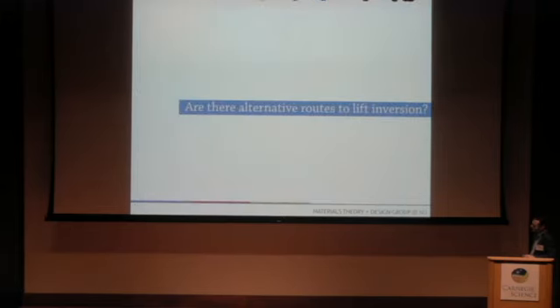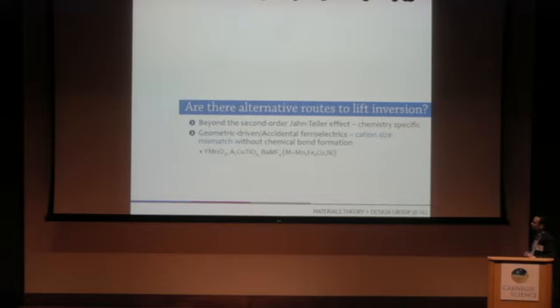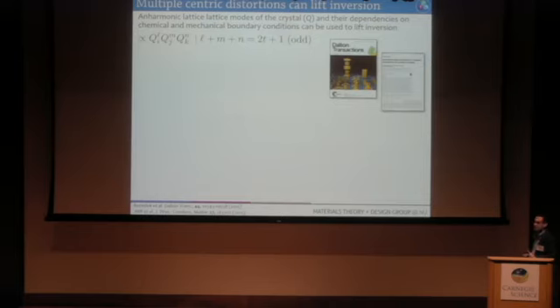Okay, so are there alternative routes to lift inversion symmetry? And let me give you a little context for this. So what we're doing is trying to look for beyond second-order Jahn-Teller effects, so things outside of chemistry. Can we structurally lift inversion symmetry? And this is also considered an area in chemistry as geometric-driven or accidental ferroelectrics. And we've heard about some of these improper ferroelectrics already at this meeting. And so let me give you a little slant on how I view this. One way we can additionally lift inversion symmetry is through this idea of multi-mode coupling. Okay, and so the idea is that you can have multiple modes, here represented as Q, which are interacting with each other, and in combination, they can lift the necessary symmetries that preserve, say, inversion symmetry.